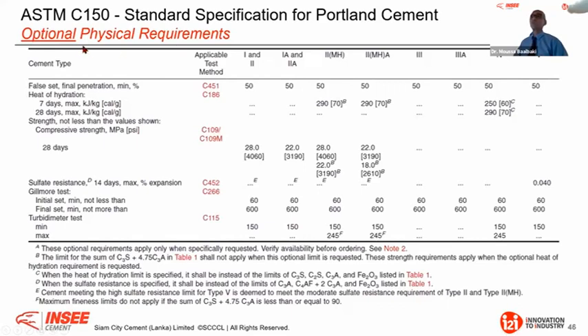Now, these are the optional physical requirements, table 4, that is the performance base. Therefore, what it says is that, for example, if you do a false set test, and your final penetration is 50%, for SO3 you can increase the amount, no problem. For the heat of hydration, regarding C3A you can exceed the limit if you can assure that for your moderate heat and moderate sulfate you have 290 for the heat at 7 days, and for low heat cement it is 250, and 290 at 28 days. This is performance based. It's not prescriptive, it's really performance based, because you do the test and you look at your performance.